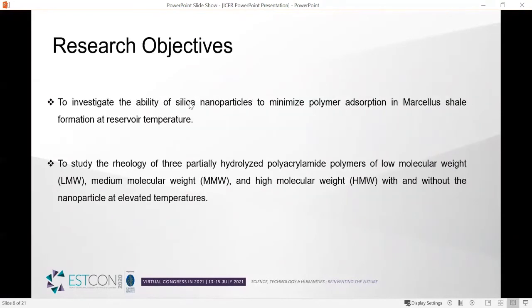So from that, we can look at the objectives. Our objective is to investigate the ability of the silica nanoparticles to minimize the polymer adsorption in Marcellus shale formation at reservoir temperature, as well as to study the rheology of the three partially hydrolyzed polyacrylamide polymers of low, medium, and high molecular weight with and without the nanoparticle at elevated temperature.